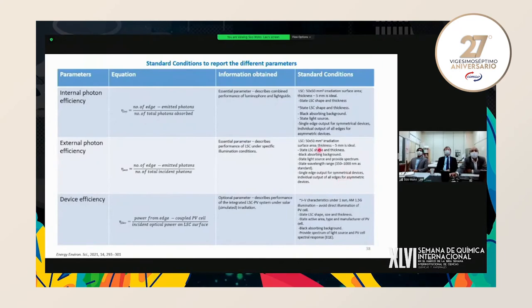Until now, there is no standard for these LSCs. Here we have internal photon efficiency, external photon efficiency, and device efficiency. If we use a similar device having the same dimensions, like 50 by 50 mm square and 5 mm thick, it will be ideal, so we can compare with others' materials. And for device efficiency, if we use one sun, meaning 100 milliwatt per centimeter square light irradiation, and this should be consistent across every researcher, then we can compare.